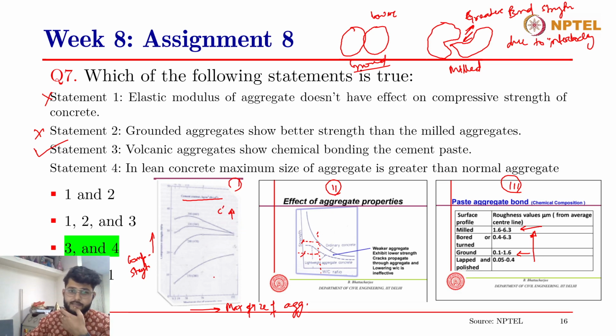Cement content is increasing as we move from low to high on the y-axis, and you can see that when the cement content is low, as you increase the maximum size of the aggregate, the compressive strength somewhat increases, right? So this is the case of lean concretes when the cement content is low. As you further increase the cement content, and then keep on increasing the maximum size of aggregates, the compressive strength of the concrete increases till a given value and then remains constant.